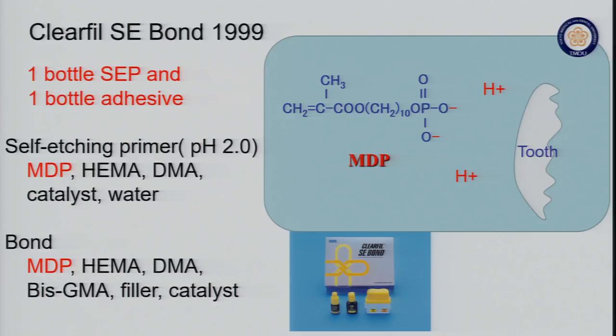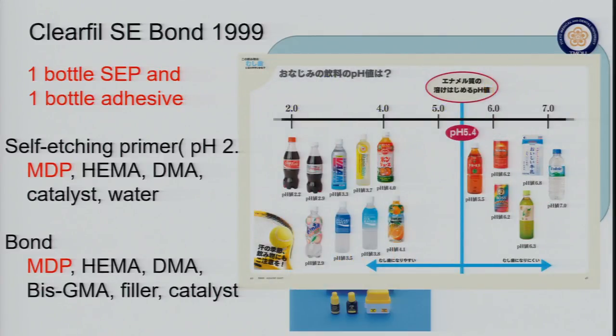That's why we need a small amount of water. However, the water cannot be polymerized. That's why after the application, we remove the excess of the primer by air blasting. Of course, HEMA, a hydrophilic monomer, and hydrophobic monomers are incorporated. Again, the self-etching primer can etch the tooth surface, and we expect a chemical reaction to occur between this monomer and the calcium ions from the hydroxyapatite. pH 2.0 is strong enough to etch the surface of enamel and dentin.